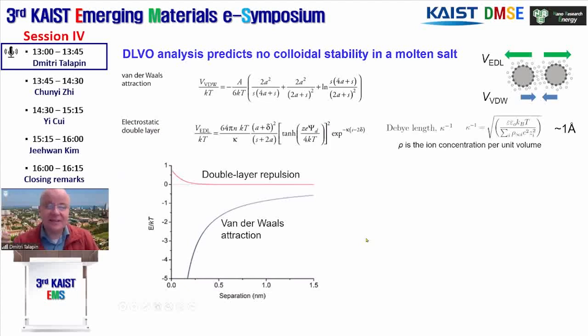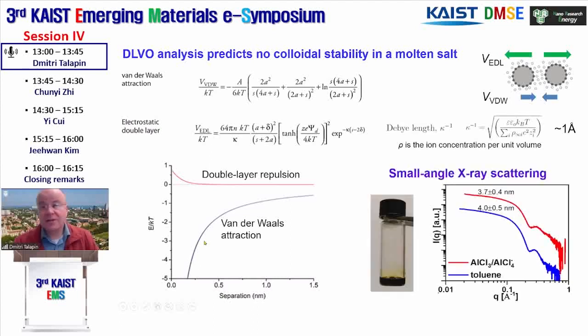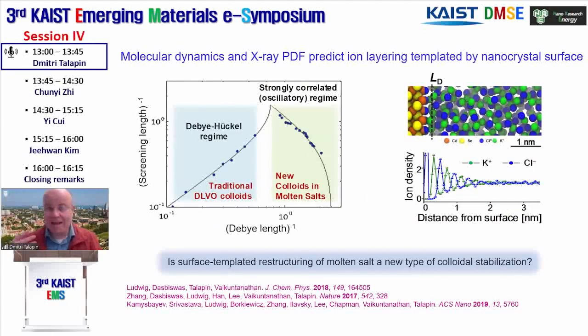In other words, the double layer repulsion will always be inferior to van der Waals attraction in every model that we dealt with. On the other hand, we found that these colloids do exist, and we can prove it by a variety of experimental methods. So in order to understand it better, we did a lot of theoretical analysis, we did Monte Carlo and molecular dynamics simulations, we did hard X-ray pair distribution function analysis, or so-called double differential pair distribution function analysis, to understand what's going on. And it looks like